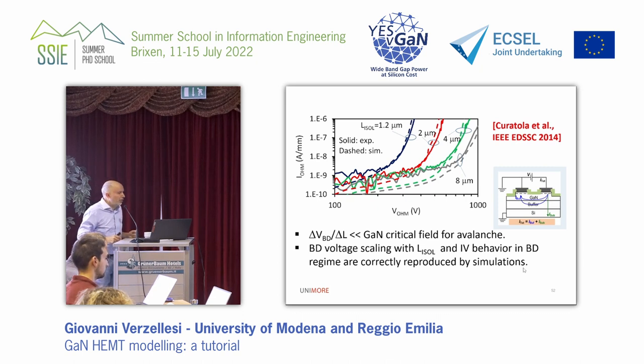And here you have experiments and simulations in very good agreement, and simulations are very simple. Basically, nothing different than simple source to drain punch through. At some critical VDS, carbon doping is not able to suppress the leakage current anymore. And this basically controls the breakdown voltage, defined at a very demanding Infineon-style level, very low drain current.